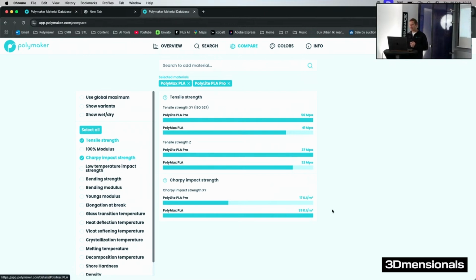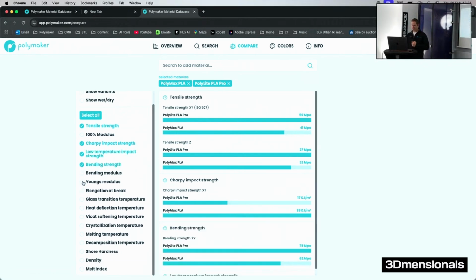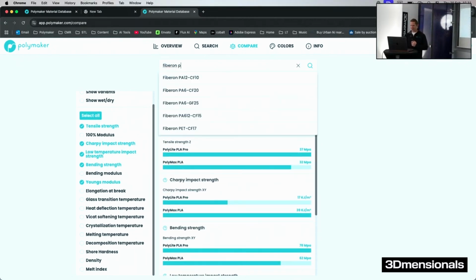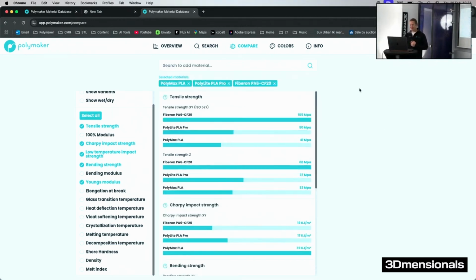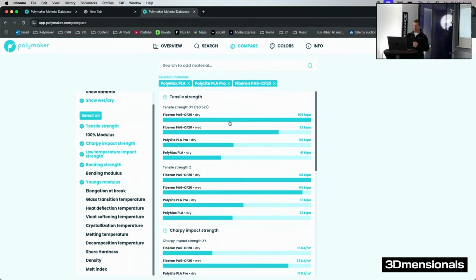You see that in terms of impact strength, Polymax PLA is really outperforming, whereas PLA Pro has slightly better layer adhesion on the Z-axis tensile strength. Then you can select as many properties as you like here and really get a full comparison. You can add more materials in here, PA6 for example. Now we see PA6 is really the best performing in terms of tensile strength. We also have wet and dry results here.